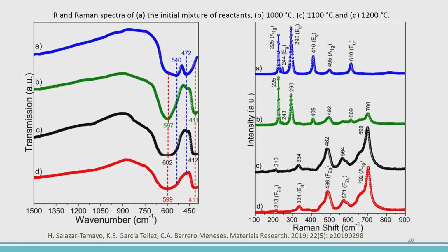Now we can do the same with infrared. This is for the mixture, so I'm just going to concentrate on the thermally treated samples. We notice that this first band is due to iron-oxygen stretching vibrations on the tetrahedral, and this is on the octahedral. And we notice that the octahedral increases slightly in intensity. We can do that also by fitting this Raman spectra, but we did not.